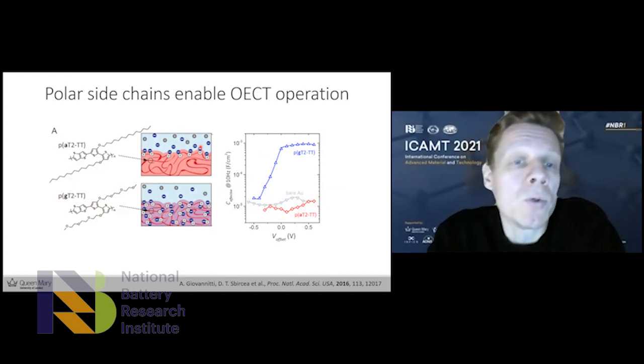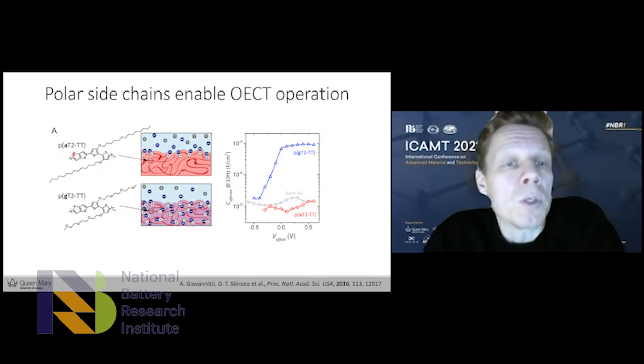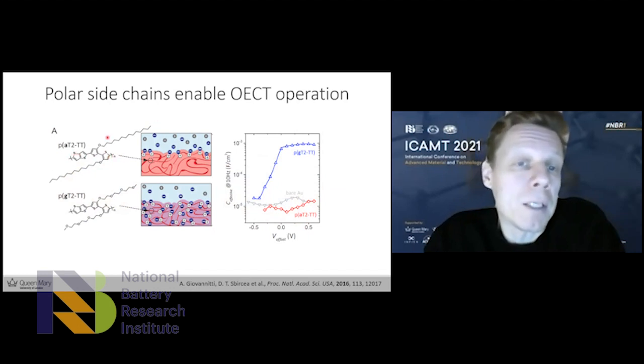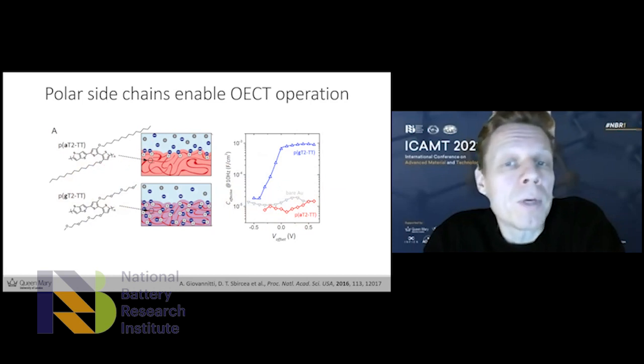Here's a cartoon where we compared two different polymers. The one I showed on the left before, where we just have the polymer backbone and aliphatic side chains. We can see we get an OFET-type operation, where we only get charge accumulation at the interface between the electrolyte and the semiconductor film, and the effective capacitance is quite low. We don't see much increase in the capacitance as we increase the bias.